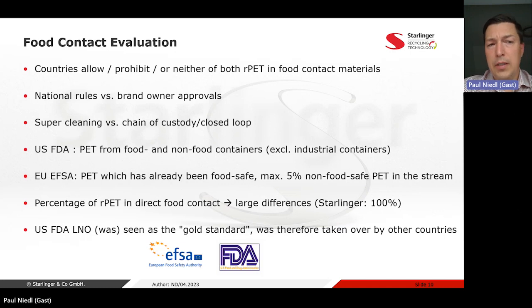And last but not least, what I would like to mention on this slide, when you compare, for instance, the FDA letters of non-objection, there are also very large differences, because if you're not going to dig inside, you're not going to find out what's the allowed rate at which you can really use the pellets back into new bottles and new preforms. And this is determined by the super cleaning technology that you're using. I can proudly say that all the various FDA LNOs that Starlinger has in place, all of them produce rPET which can be reused in the percentage of 100% back into preforms and bottles.